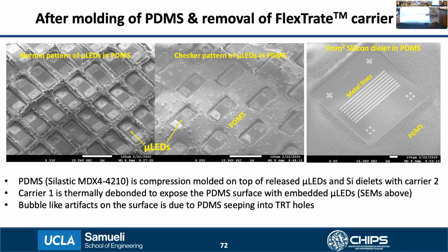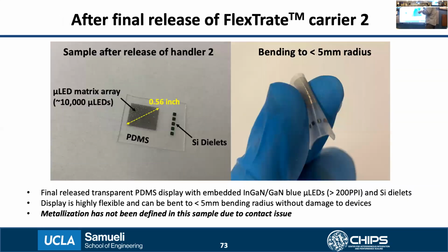Next, once these LEDs are embedded in the PDMS, we debond the second handler. So here you see the sample after the full thermal debonding of the second handler with this flexible PDMS, which has around 10,000 micro LEDs embedded in it at 300 ppi resolution. And here you see me bending it to less than 5 millimeter bending radius without any damage to the devices. So at the moment, for this particular sample, the metallization has not been defined because of the contact delamination issue.